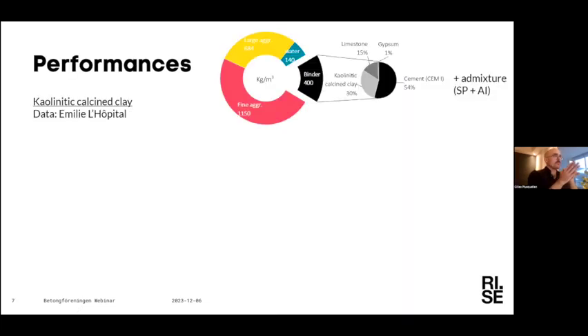Now I'm going to give some indication of the type of performances that we can hope for when using this kind of concrete with clays. I'm going to show you values for kaolinitic calcined clays, and with this specific binder, say mix design, sorry. So for the binder, we have a replacement rate of about 50%, with 30% of calcined kaolinitic clays and 15% limestone. And of course, the results really depend on those parameters here, especially the water and the type and amount of admixture that you put there. But it still gives an idea of what we can reach.